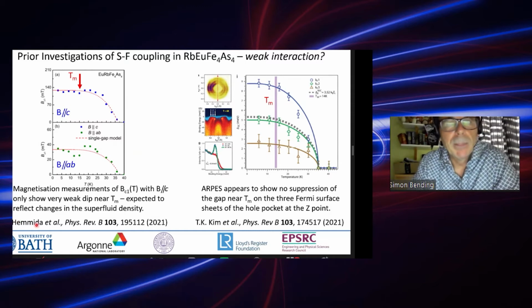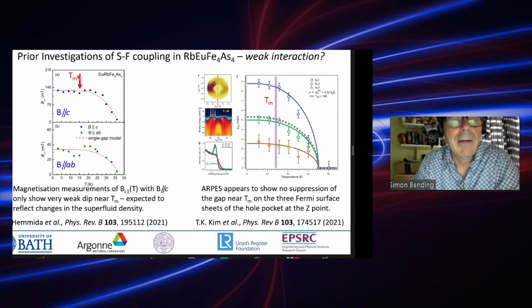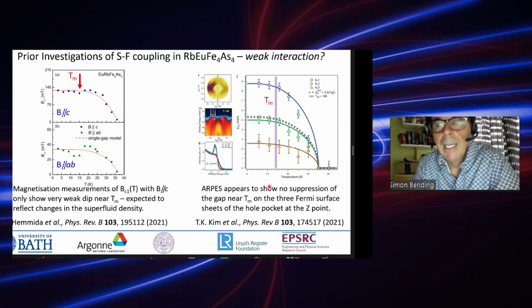There are some very recent magnetization measurements by Hemmida et al., where, for example, they've measured BC1, the lower critical field, in 2 different orthogonal directions. The most interesting one for me probably is where B is parallel to the c-axis. And you can see that maybe there's a very small dip in BC1 here at the magnetic ordering temperature, but nothing really that's very significant. And you would expect this dip to be directly reflecting any change in the superfluid density. So you might infer from that the superfluid density changes very little at the magnetic ordering temperature.